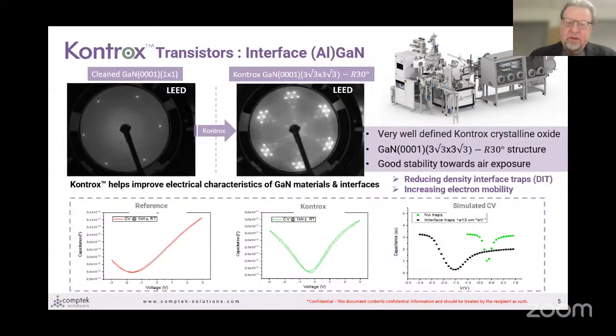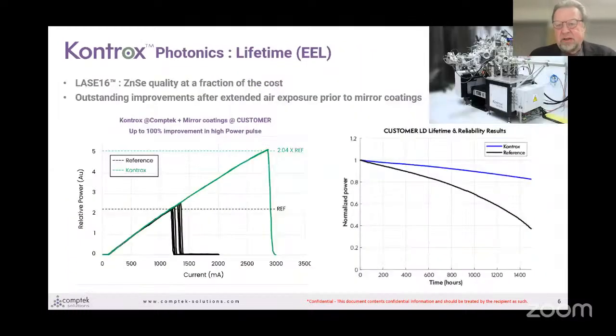Another example of this technology is the lifetime, and here I use high power lasers as an example. You can see on the picture on the right that after almost 1000, or 500 hours, a Kontrox passivated laser bar maintains a relatively high power level compared to the standard reference method that is being used in this example by the customer.